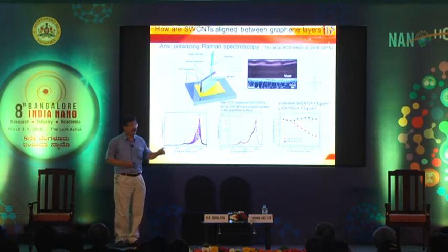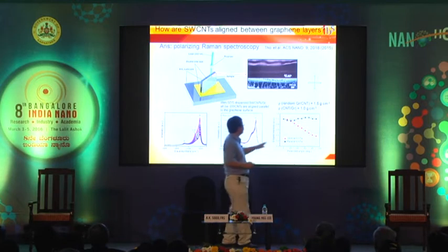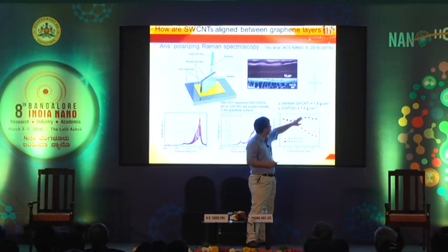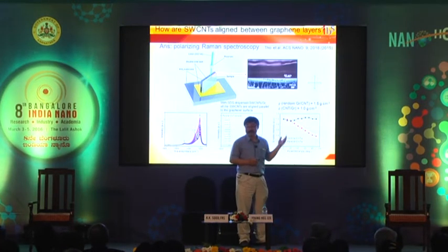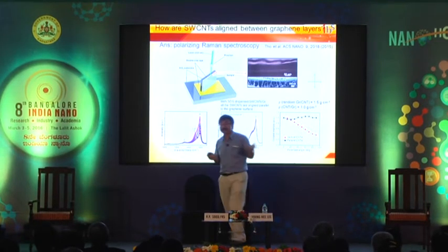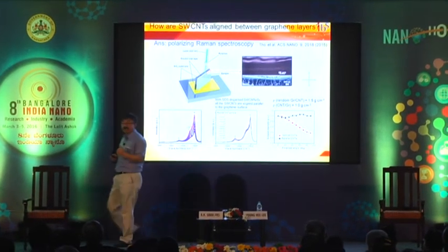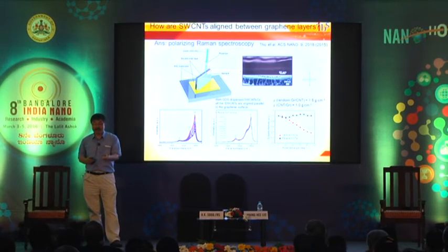And one thing that I'd like to emphasize is the density of the sample. The density, in this case, is 1 gram per cubic centimeter, which is very high, even though this is highly porous. So this is the key. Then you can have both volumetric and gravimetric values very high.